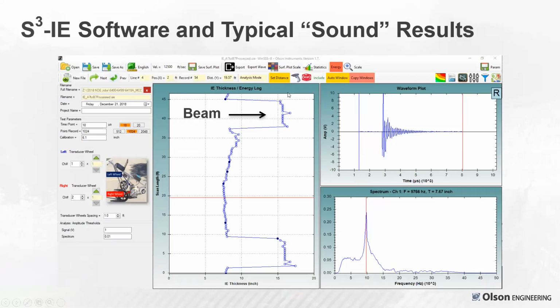And this is a screenshot from the S-cubed software showing a typical single scan line. As you can see, it's over 45 feet long starting here. So we have the nominal thickness of just the slab at around 8 inches. Then we have the thickness of a beam at around 16 to 17 inches, going back to the slab, some variation in thickness, that's pretty normal. And then back to a beam, back to a slab. You can see that there's quite a few test points within this record. There's over 100 points just in this single scan.